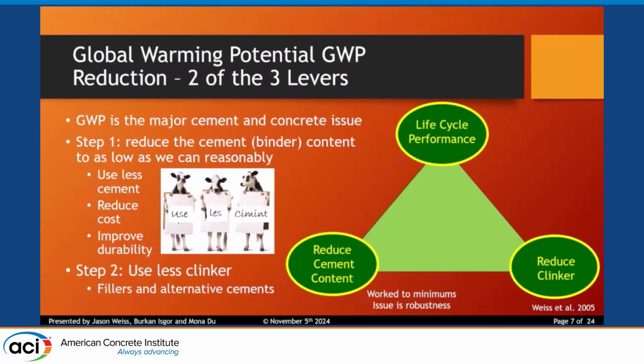So what we've been doing for the last 15 or so years is saying there are really three big pushes we need to make when we talk about long-term sustainability. The first is we need to reduce the cement content in our mixtures, and many agencies have started to do this. They've started to reduce minimum cement contents, optimize aggregations, and encourage pushing that value down. Now that is awesome, and there's been huge progress made, with agencies taking 50 or 100 pounds of cement out of their mixture and getting very equivalent performance.